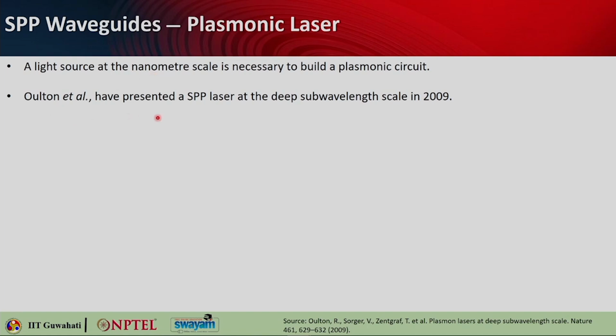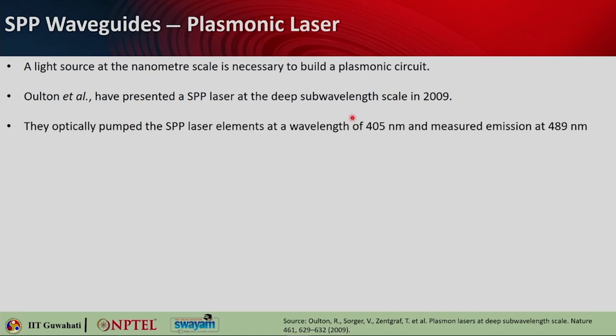Oulton and colleagues presented an SPP laser at the deep sub-wavelength scale in 2009, and they optically pumped the SPP laser elements at a wavelength of 405 nanometer, and they found emission at 489 nanometer.